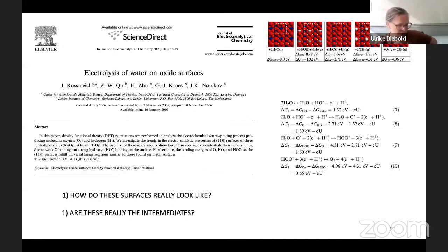So we look at what's called the surface reconstruction, that's the geometry change of the surface. We know, for example, that the TiO2 110 surface is fine. It turns out that for the iridium oxide surface, the 110 is in fact not. We published a paper together with Karsten Reuter last year. For iridium oxide, the 110 is not the lowest surface energy. The 011 is, which is a different surface, and actually that reconstructs, right? So there's a lot of things to be known. I cannot answer this in general. I can answer for the ones we've looked at.